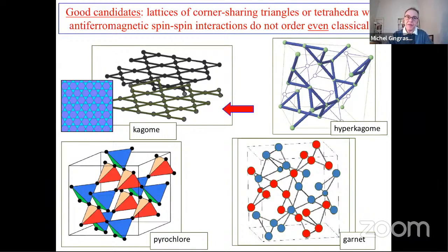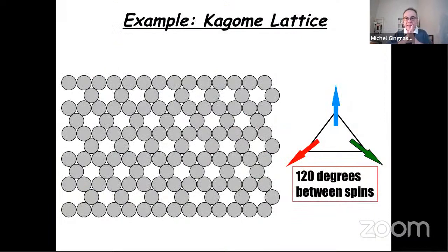So let me illustrate that for the Kagome lattice, because the idea here that I will illustrate will be very important for spin ice. So if you consider a Kagome lattice of corner-sharing triangles, and on each site you have a magnetic moment that interacts with an antiferromagnetic interaction, if you want to minimize the energy on each elementary triangular unit, one way to illustrate the classical ground state construction, neglecting continuous fluctuations, just the discrete part of the manifold, is you color the lattice. With a coloring rule: each site has one of three colors, blue, red, or green, with the additional rule that no site has a neighbor of the same color.